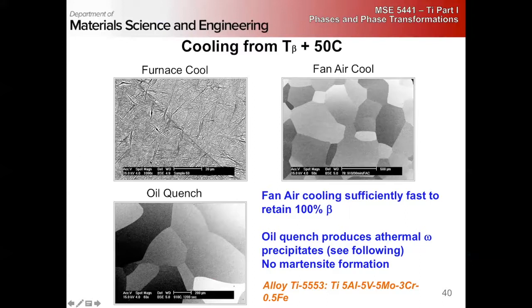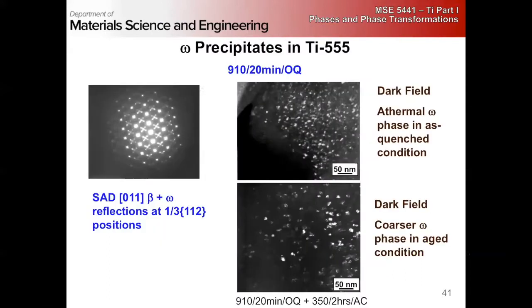On the oil quench, in this alloy, we'll get an athermal omega fraction. And so just the omega as we saw it before, we get this very fine dispersion of omega in the as quenched condition. Then as we age it, this will coarsen. So the oil quench, and then this is 2 hours aging at 350 C, so not a very high temperature to coarsen.